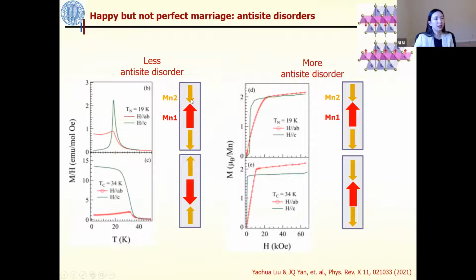Therefore, neutron scattering shows that for the 124, when you dope antimony inside, because of the smaller radius difference between manganese and antimony, they tend to form a larger antisite disorder. From the study of this manganese antimony 2 tellurium 4, which is the extreme case here, they found that the manganese 2 sites are always antiferromagnetically coupled with the manganese 1 site. They found that if there is less antisite disorder, the manganese 2 sublattice by itself is antiferromagnetically coupled, and the manganese 1 sublattice by itself is antiferromagnetically coupled. These two individual sublattices are antiferromagnetically coupled with each other.